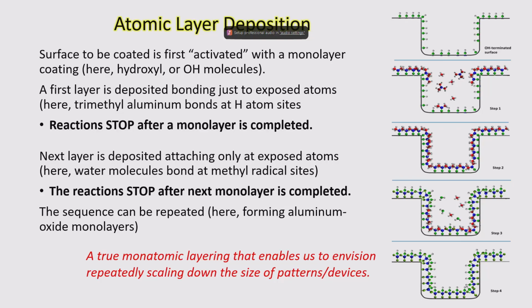So you'll have a nice molecular layer of material that's deposited by this chemical. Then next you can do a simple exposure to water, and it will bond again, but only at those individual sites. So layer by layer, and then you can continue the process. Layer, next layer, and you can build up atomic layers of material. So this is very important in being able to scale down devices to ever smaller levels that are necessary in order to produce, for example, semiconductor chips.